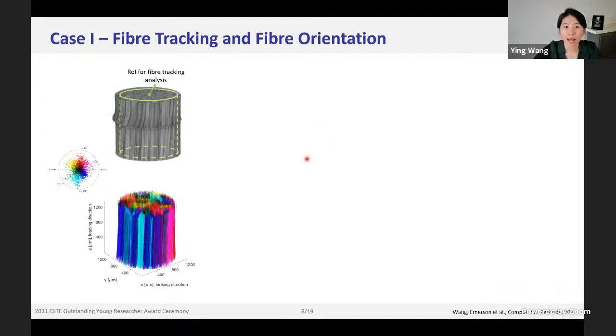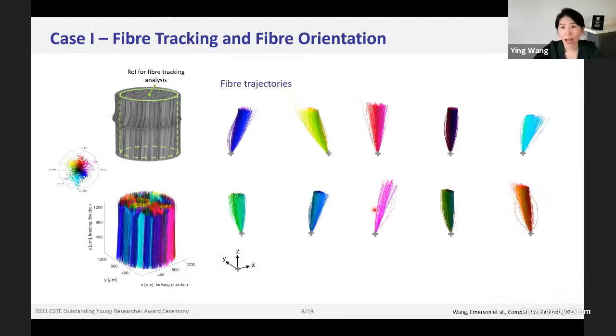And you see the color lines here. Each line represents the center line of an individual fiber. In this case, we can see that all of the fibers have different orientations. And even if they have similar colors, which means they have similar orientations, the waviness and the shape of the fibers can still be very different. This indicates the scatter in the initial fiber status. And we also look at when the fibers are deformed under load, the fiber tracks also look very different because the initial status is different.